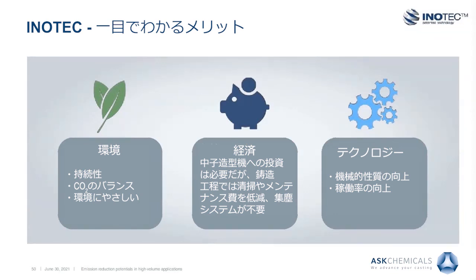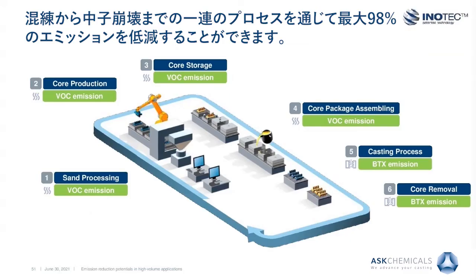In summary, the INOTEC Trinity concludes the ecological, economic, and technological benefits of the binder system. INOTEC is clearly an emission-free alternative to conventional organic binder systems like cold box, more suitable and more environmentally friendly. The initial higher investment for the equipment of core manufacturing is compensated along the process chain by savings in maintenance, the lack of air treatment systems, and the higher productivity at the die. Technological benefits rely on improved dynamic properties of the casting, enabling downsizing and lightweight construction. INOTEC is able to reduce both VOC emissions as well as BTX emissions by up to 98% along the complete casting process chain and is your industry standard for emission-free applications.